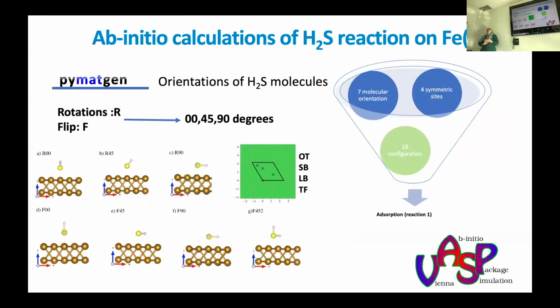Now we come to the challenge or the question from the industry, which was about the effect of H2S. Now that we made sure that we are capturing the main phenomena pretty well, when we come to H2S, H2S is a little bit larger than CO2, and the orientation of the molecule matters a lot. So we face the following challenge: in terms of adsorption energy, it is not that simple compared to the case of the CO molecule, because we have 7 molecular orientations and we have